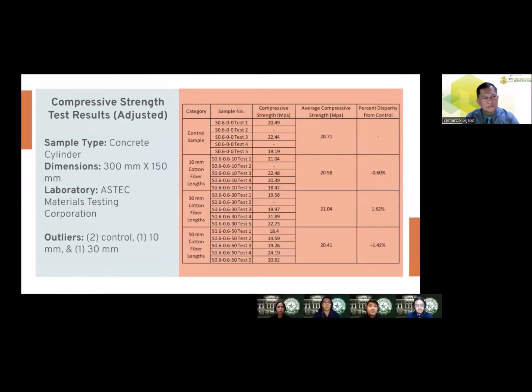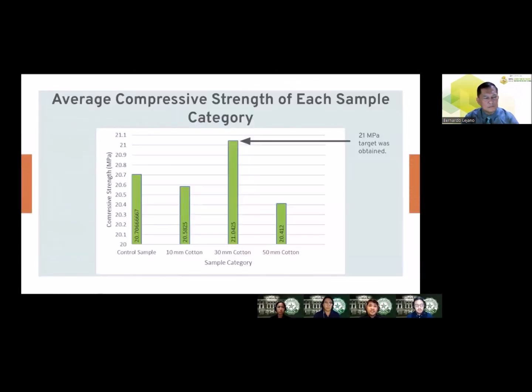As for the compressive test results, the samples were tested in ASTEC Materials Testing Corporation in the Cavite laboratory location. Outliers were taken out, and the average compressive strength is adjusted accordingly. From the control to the 50 mm samples, it is seen that the adjusted average compressive strengths are 20.71, 20.58, 21.04, and 20.41 MPa respectively. To further visualize the differences in the strength, here is a graph that shows the comparison of the 4 cases.